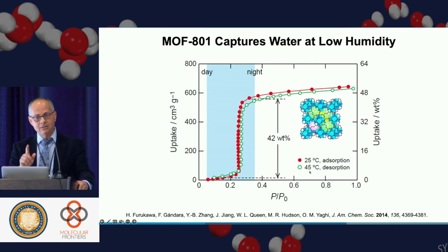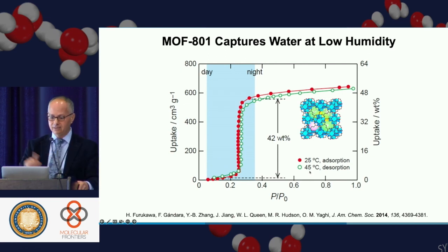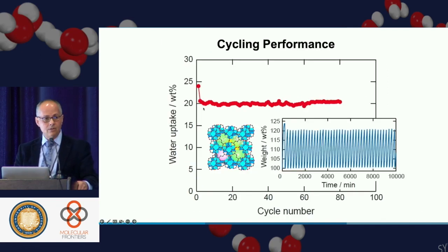Now, we all know zeolites take up water from low humidity, but you have to heat them up to 200, 300 degrees Celsius to get the water out because they're very hydrophilic. But here, you don't, because you have the organic units and the inorganic units, the hydrophilic and the hydrophobic, modulating how strongly the water is bound into the pores. Okay, so we tried then, we cycled the water in and out of the material, and you see here a very nice uptake and release up to 80 cycles here.